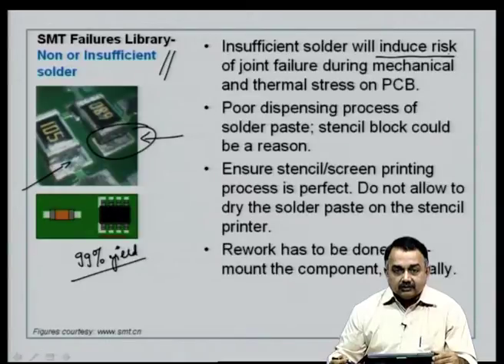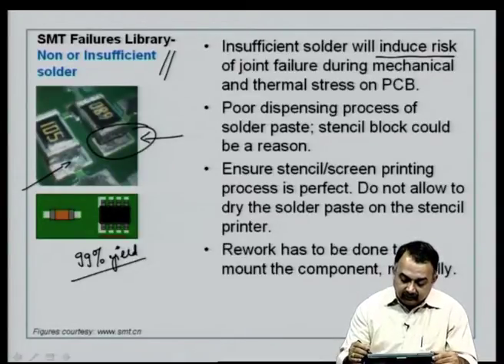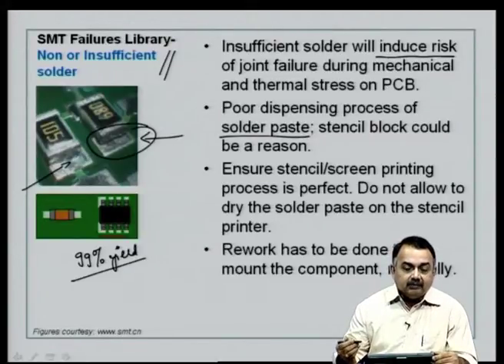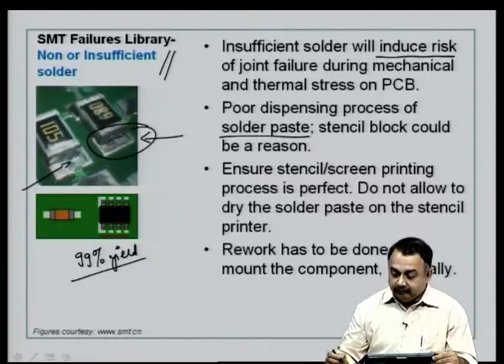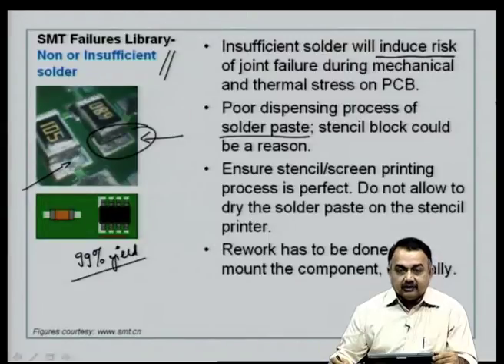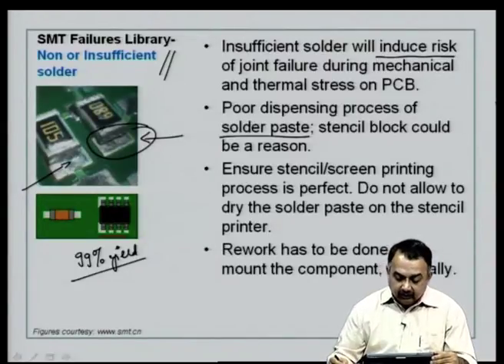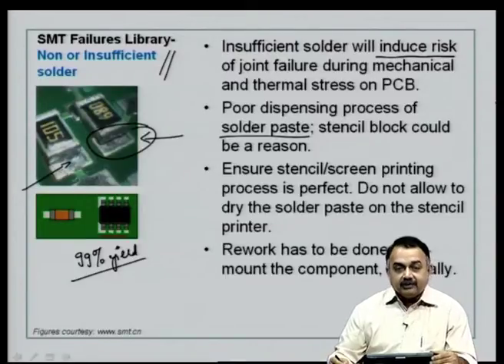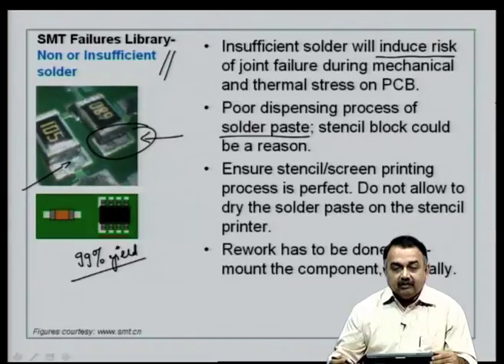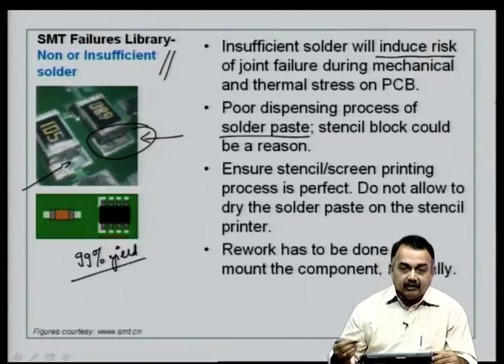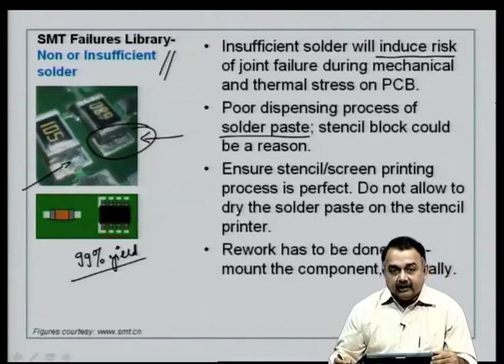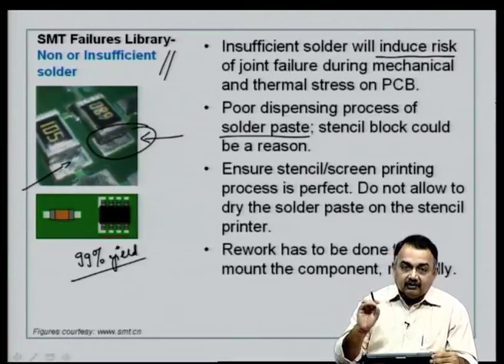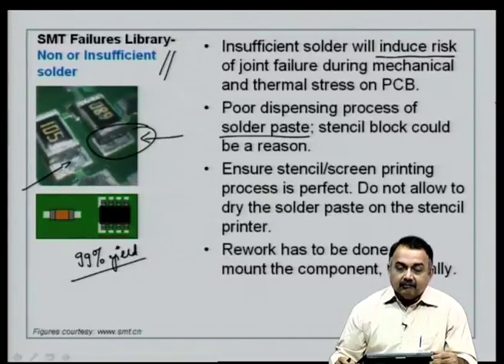Now, how do you control this? The important area where you would need to control is the dispensing process of the solder paste. Remember, you are dispensing solder paste using stencil or screen printing, better done by stencil printing using stainless steel stencils. Now, the stencil could be blocked for some reason, because either you have done too much printing on that particular stencil, the solder paste could have dried, and you have not really cared to clean the openings on the stencil, so that the solder paste flow onto the PCB is continuous and consistent.